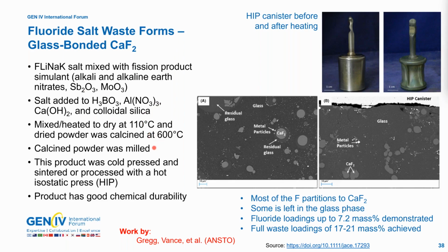This calcined powder was milled, and then they were either cold pressed, sintered, or hipped. And this is a really neat system because they found that the fluorine was partitioning to calcium fluoride. So it's reacting with this calcium hydroxide phase to form environmentally stable calcium fluoride inclusions within their glass, encapsulated by the glass phase.